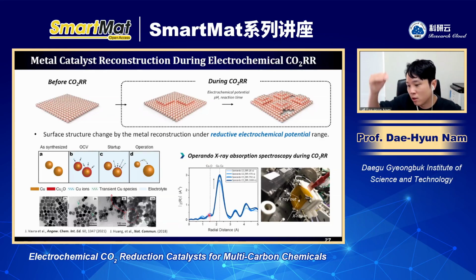This indicates lowering the number of the copper-oxygen bonding. And we can see the increase of some peak in this copper. It means some copper bonding increases. This is related with some reductive potential-induced copper reconstruction. So we need to figure out how we can manage this kind of reconstruction. So the second chapter is related with this kind of phenomena.